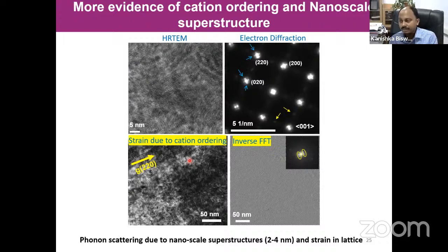So where are the strain ripples coming from? Now, if you remember the slide where Mohanty proposed, this ordering can happen in different directions, right? In this compound, this will create similar energy or similar lower energy ordered structures, which will be sitting in different local minima of the energy diagram, because ordering can happen in cell doubling or cell tripling or many other ways. But those will have similar lattice parameters. Once we have similar lattice parameters and similar energy structures, the compound can go and sit in different kinetic minima or low energy minima, right? Once it happens, it will create huge strain in the lattice. And that's what we are seeing in that TEM, and that tells that basically this ordering of atoms actually creates this strain in the lattice, and that is very good to decrease the thermal conductivity.